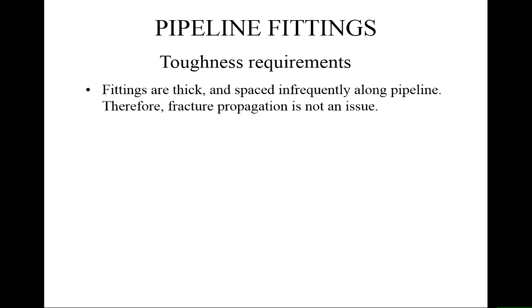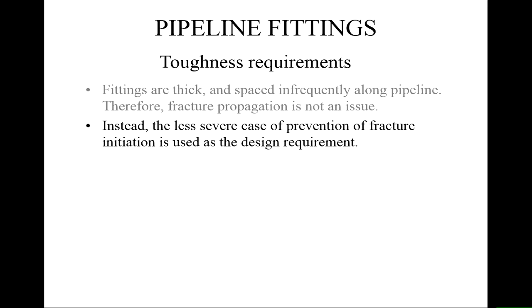Toughness requirements: the fittings are thick. Generally, they're spaced infrequently along the pipeline. So generally, in a fitting, fracture propagation is not an issue. If the crack runs along the pipeline and comes to a fitting, it tends to stop. What we don't want is the crack to start in the fitting. And so for that reason, we just tend to use a fracture initiation criterion as our design requirement, like a Charpy test.